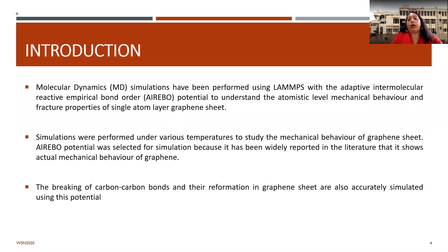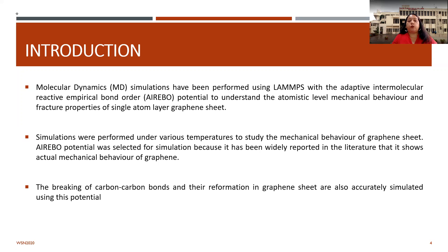Molecular dynamic simulations have been performed using LAMMPS with the adaptive intermolecular reactive empirical bond order potential to understand the atomistic-level mechanical behavior and fracture properties of single atomic layer graphene sheet. Simulations were performed under various temperatures to study the mechanical behavior of graphene sheet. The AIREBO potential was selected; it has been widely reported that it accurately shows mechanical behavior of graphene, including the breaking and reformation of carbon-carbon bonds.